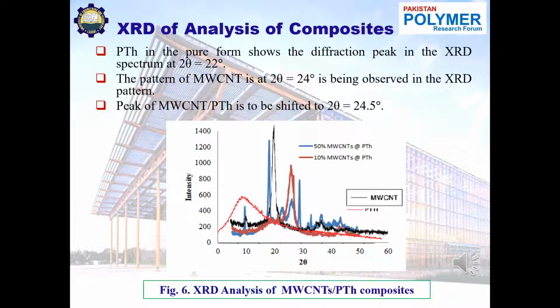Polythiophene and MWCNT composite analysis shows a broader peak at about 24.5 degrees. The broader peak is of polythiophene, and the other peak, which is the characteristic peak of MWCNT, shows the presence of MWCNT in the polythiophene matrix. The peak of MWCNT is observed to be shifted to 24.5 degrees. This result shows the interaction of MWCNT with the polythiophene matrix.